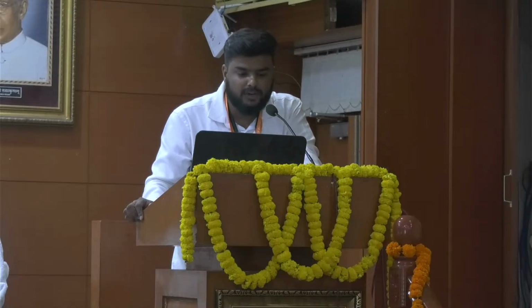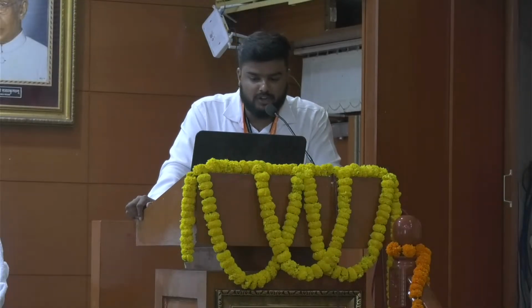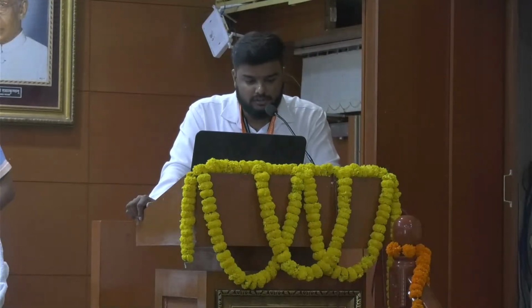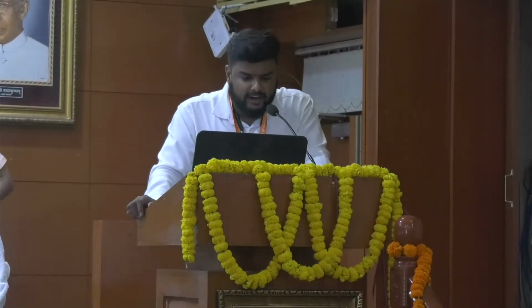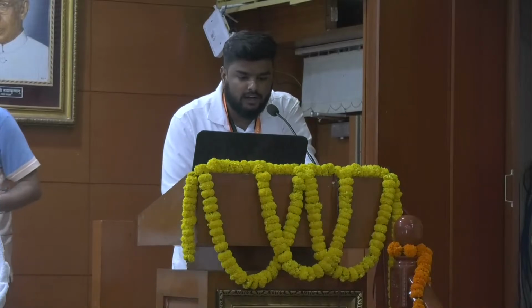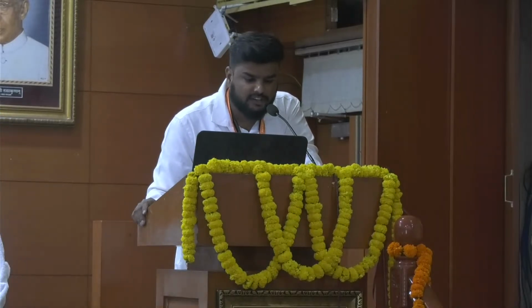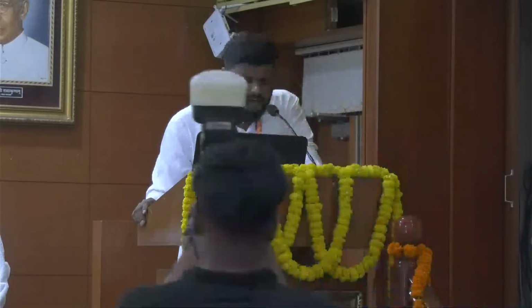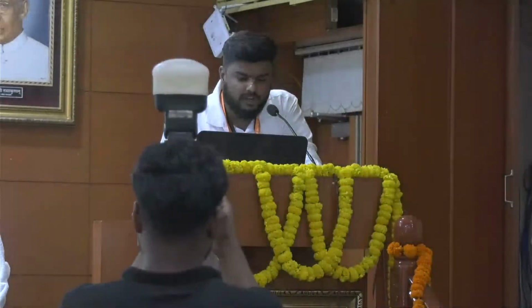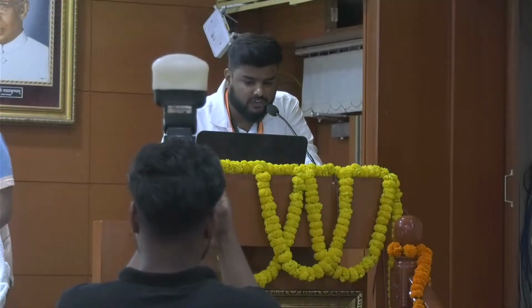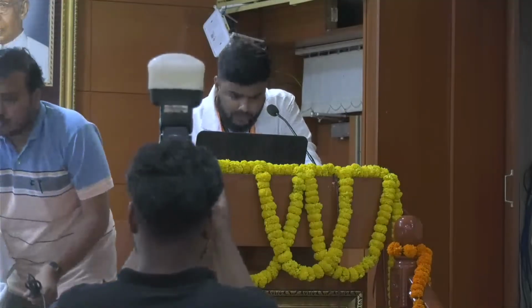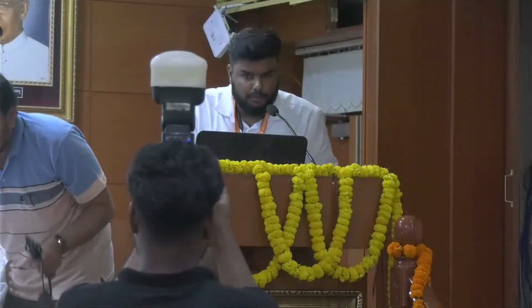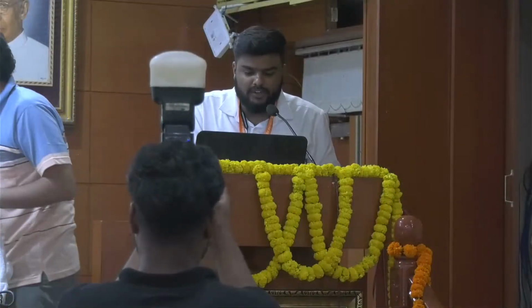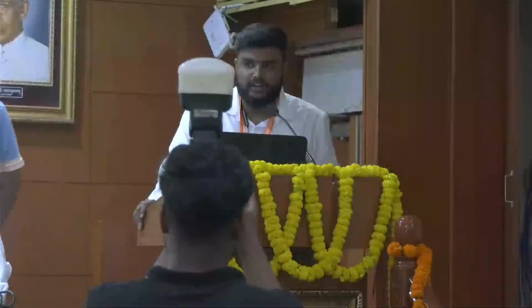I have used multiple techniques, XRD, XRF, spectroscopy, and IV analysis for evaluating the different parameters. And I have evaluated how doping alters grain and grain boundary behavior, especially resistance and capacitance of the doped material. And then I have studied the leakage current behavior across different temperatures and fields. And in the end, we have a conclusion on which dopants offer the best suppression of leakage current and improve material performance.